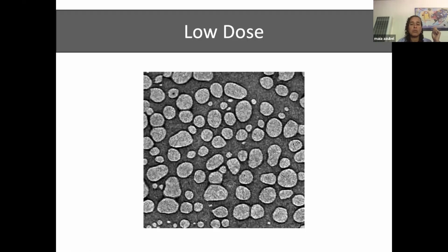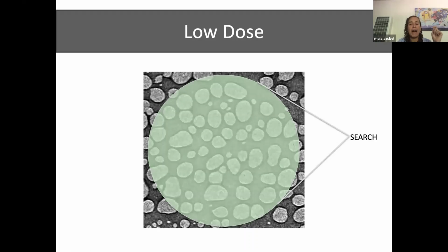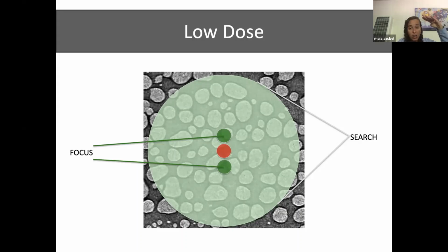What is this low dose? Well, you search at very low mag so you don't damage your sample with the beam. You select where you're going to take the image, but you don't take the image there yet. First of all, you focus on two spots that are close but do not overlap with the area that you want to take the image. And then you extrapolate the value of the focus, and only then you move the beam while it's still blocked, or you move the stage, depending on how you are working. And by the time that you take the exposure, that's the only time that your particles saw the beam. So you can control that.